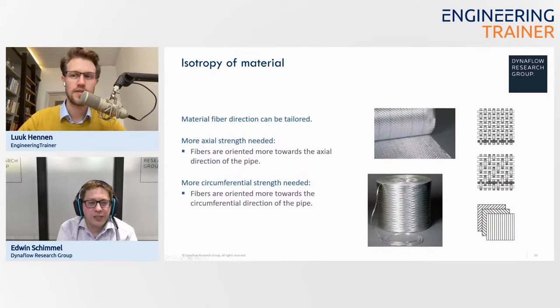But there are also applications where you need a lot of axial strength. If you have above ground piping on supports and the supports are wide apart, for example in marine applications, you have that often, then you can use piping with more axial strength. And then you also have applications where you especially need hoop strength, so you have pipes with the majority of the fibers in the hoop direction. For example, sewer piping. It's pressureless, so you mainly need hoop strength because the pipe is buried normally. So you have soil loads, and you also have vehicle loads crossing above ground over the pipe. So then you add more fibers in the hoop direction, and then it's strong in the hoop direction. So you can really tailor for whatever you need.